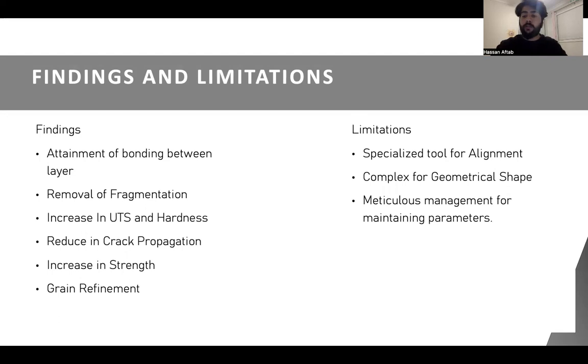The redistribution of strain and the presence of a gradient microstructure result in a more favorable stress distribution and resistance to crack initiation and propagation. It results in an overall increase in the material strength. The combination of factors such as grain refinement, bonding between layers, and reduced fragmentation contributes to enhanced strength characteristics. ARB achieves grain refinement in the material. The asymmetrical deformation induces strain localization and promotes the refinement of the grain structure.